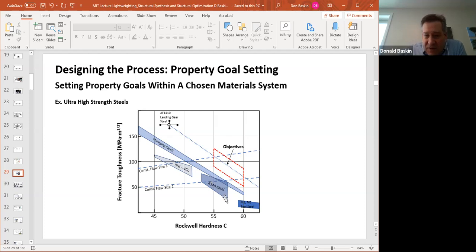And you can see where that falls in this paradigm of toughness and strength. Strength, again, is the same as hardness. You can easily get a 4340 to a strength of, I don't know, 55 Rockwell C and still have a fracture toughness of about 50 megapascal root meters. On the other end of the spectrum, you have this material right here called AF1410. This is a special, I think 6 or 7 component, alloy steel with cobalt, chrome, nickel, moly. And this is a material that was specifically developed by the Air Force, that's why it says AF in front of it, to be used in landing gear.